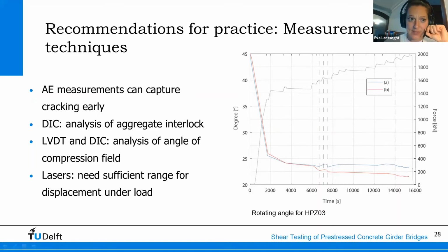We've also learned from our measurements that the acoustic emission measurements can capture cracking early, before any of the other methods. That we can have an insight into the shear carrying mechanisms by using digital image correlation, and in particular, the analysis with aggregate interlock. We've been able to look and to actually confirm how the compression field rotates further downward. And we also learned that if we want to measure the displacement under the load, we need a sufficient range with the laser distance finders.